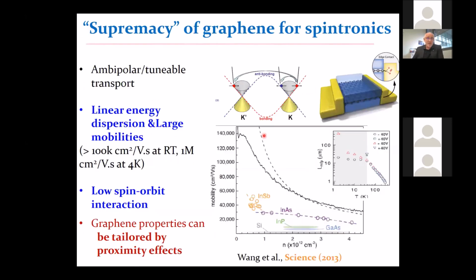Early on, graphene, and Albert anticipated that, was envisioned to be an ideal material for transporting spin information, for the following reasons: it was a material with a very low spin-orbit coupling, and also a very long mean free path or large mobility. Combining both, we were expecting that it would be an ideal platform for moving electrons and spin information. At the same time, being just a surface, it was also clear that maybe we could enrich the properties of graphene and make it magnetic somehow, or spin active, just by very weak proximity effect. And this turned out to be one of the major aspects and interests of this two-dimensional material.